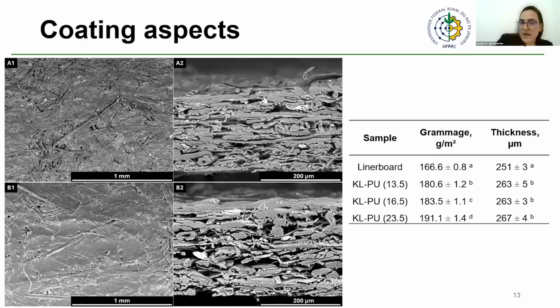And we also evaluated the paper grammage and thickness. As we expected, as we tested 3 different grammages, the grammage of each was different, and the grammage increased with the coating weight. But when we looked at the thickness, statistically they didn't differ from each other. Probably because of the paper structure, which is a high porosity paper, and probably the coating was absorbed by the paper and made the thickness of them the same.